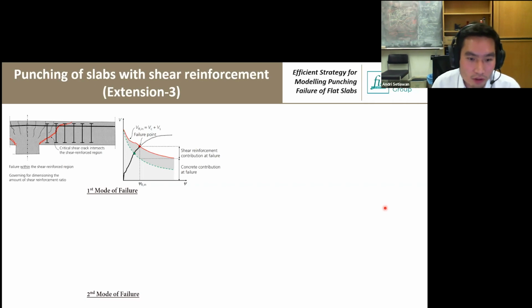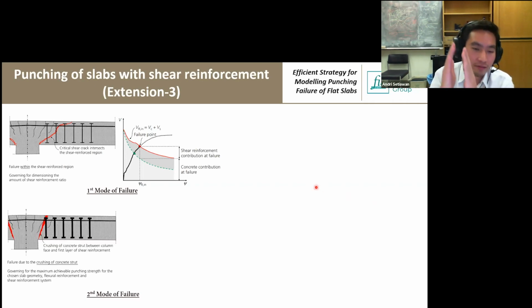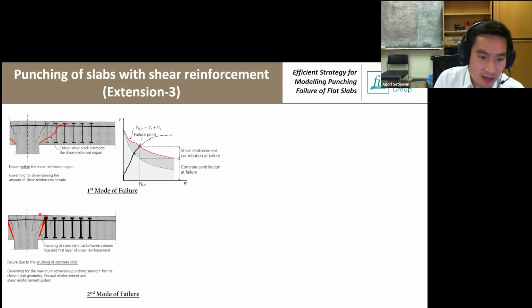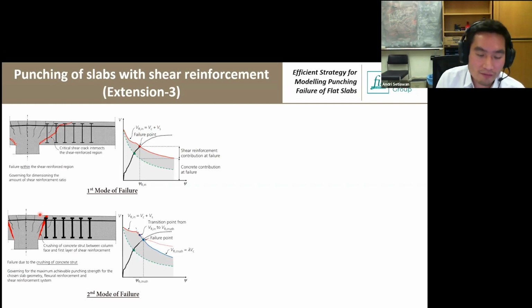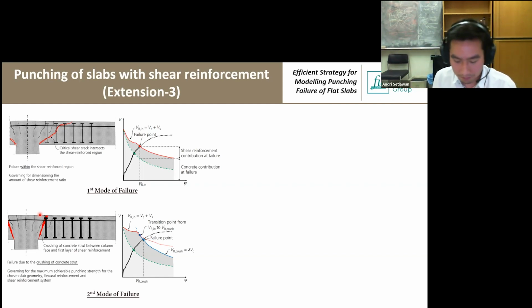The second mode of failure is when you have a large diameter of shear reinforcement with a narrow spacing, so the crack is not going to propagate into the shear reinforced zone. Instead, the failure will happen by the crushing of concrete at the inner face of the slab. In this scenario, we also have a criterion, which is basically a function of the detailing and the anchorage condition of the reinforcement, the spacing, and also the concrete strength.